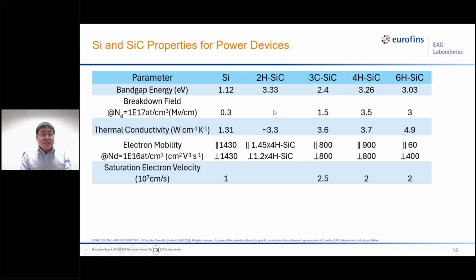So here it summarizes the physical properties of silicon carbide and silicon. As you can see here, all silicon carbide has a higher band gap energy than silicon, which means silicon carbide will have higher breakdown voltage. The higher breakdown field for silicon carbide than silicon means a much thinner drift layer is required to hold the same voltage. Higher thermal conductivity means the device can operate at high temperature. Higher electron mobility and electron velocity means switching faster, so it can be used in high frequency devices.